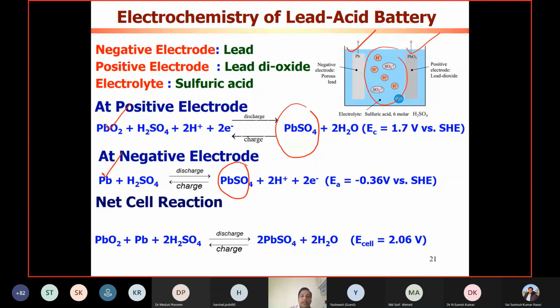Another important thing, you'll see that water. So oxygen evolution takes place at the positive electrode and the hydrogen evolution takes place at the negative electrode. And you see the voltage is 1.7 volt at the cathode and minus 0.36 volt at the anode. So that means around 0.47 volt above the decomposition potential of water, and minus 0.36 volt for the hydrogen evolution.